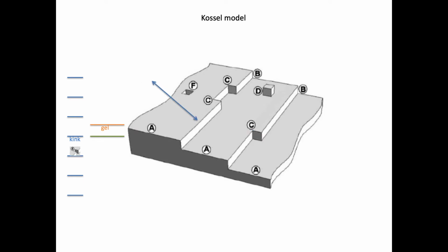If we go into a higher coordination site as we have here, well then that is very much likely to stay in the solid state and is unlikely to come back out into the gel phase now, and so we'll become stuck within the solid. And similarly, if we go to a very highly coordinated site, very unlikely that will come back out into gel. It will stay stuck there in the solid state.